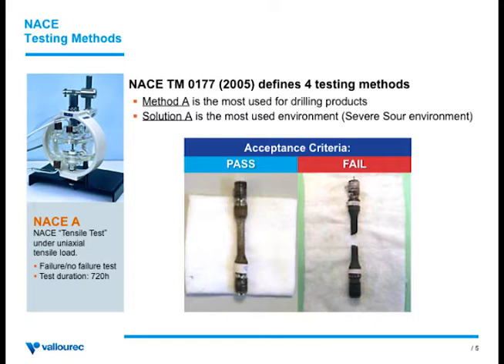That norm defines 4 testing methods. We use only one for drill pipe because it's a tensile test and it's relevant to the stresses applied to a drill pipe during the drilling operations. The test will last 720 hours, which is almost a month of testing a sample that you would take out of a drill pipe body or the tool joint or any other area on the pipe you would like to test. One month of testing under a specific content of H2S and a specific pressure.